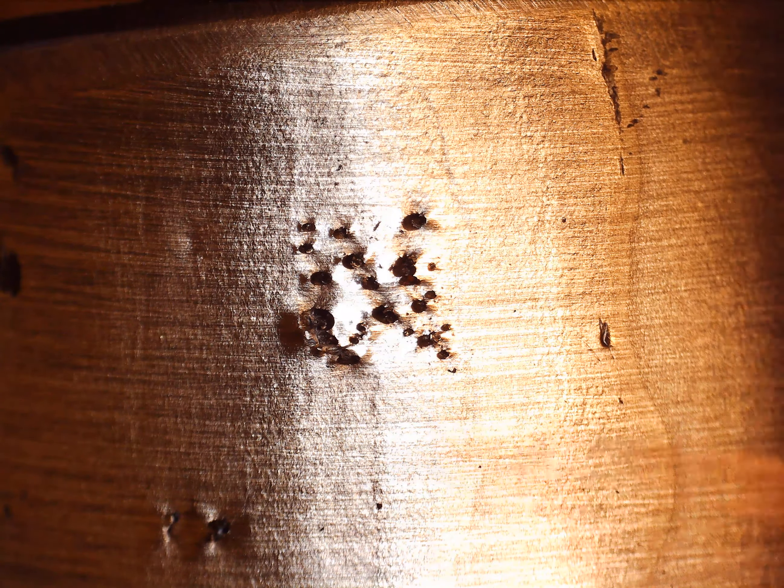This discontinuity right here, I'd say it's actually less than 1/32 inch, but we're going to go ahead and add it because we're the inspector. These right through here, these three, those are all non-relevant. This one right here, I'd say is less than 1/32 inch. I don't remember if I got that one. We're going to just go ahead and add it - one more thirty-second.